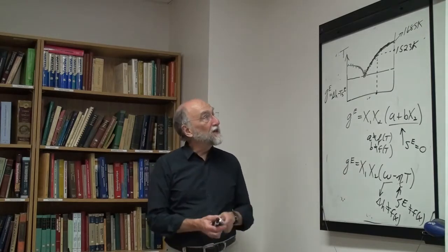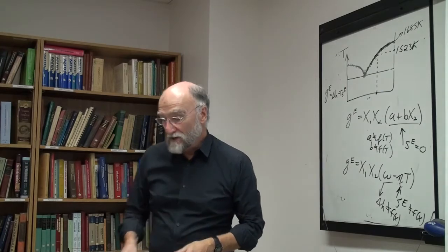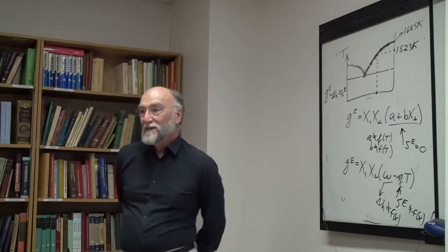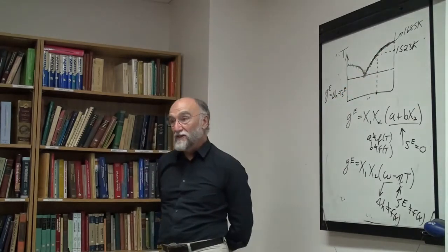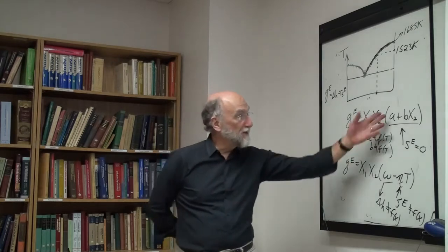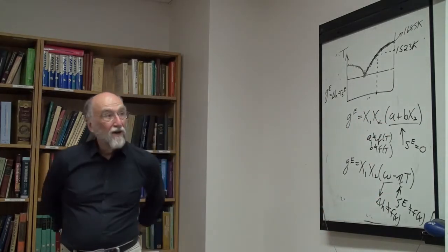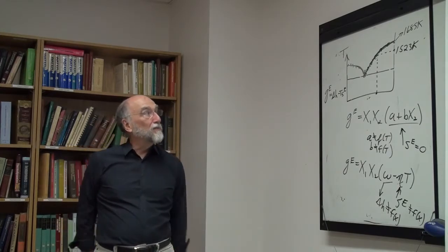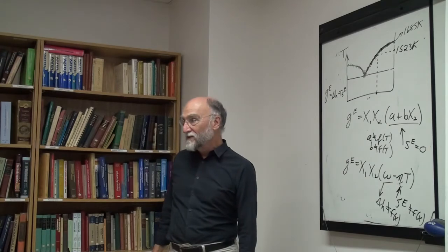Now, both cases are going to give you a good fit. You probably get just as nice a fit to the liquidus either way, but you're not going to get the same heat and entropy. So all the liquidus gives you is GXS. It doesn't give you H and SXS independently. And you can make this assumption or you can make this assumption, but this is based upon either other experimental information or upon your concept of what's probably more correct in this particular case.